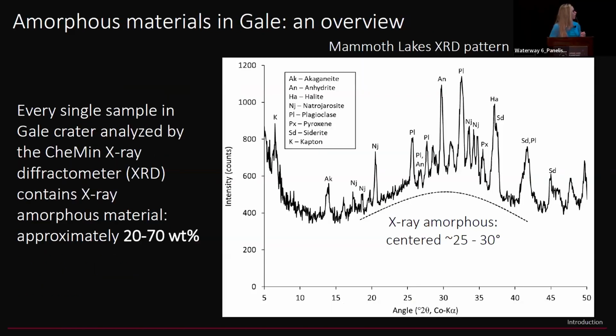So for folks who are unfamiliar with amorphous materials, every single sample that we have analyzed in Gale Crater by the CheMin XRD contains an X-ray amorphous component, and it's not a small amount either. This ranges sometimes up to 70 weight %. So this is a huge part of the sample that we're often missing information on.